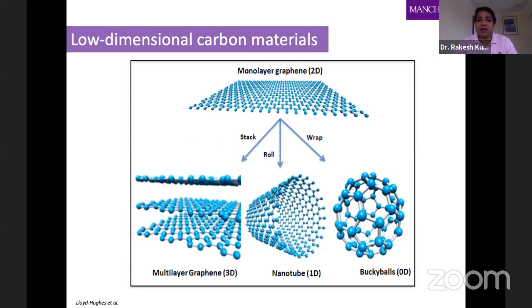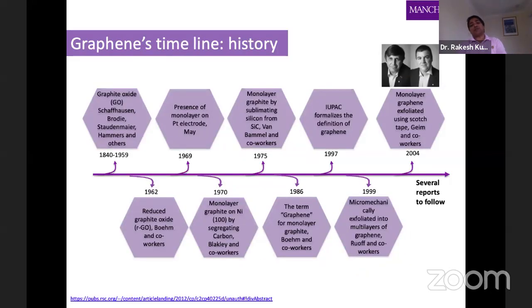So if we go back to the different types of nanomaterials, we can derive all the materials from a single layer of graphene. If we stack these graphene layers in a particular fashion, you can make a 3D stack of graphene with tunable electronic, electrical or thermal properties. Graphene can be rolled into a nanotube, and at the same time, you can pattern a buckyball out of a graphene sheet. So if you want to control the different properties, the mechanical, electrical or chemical properties, graphene can be modified to make those.